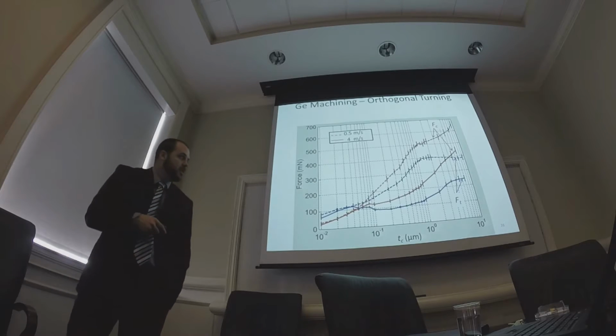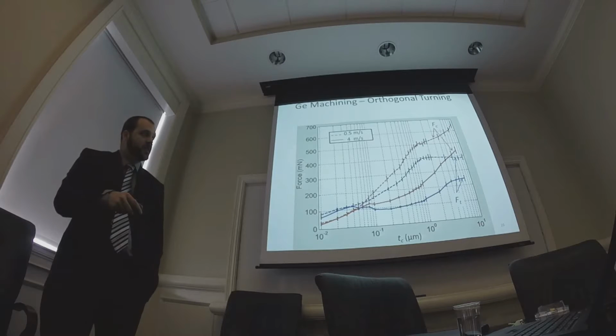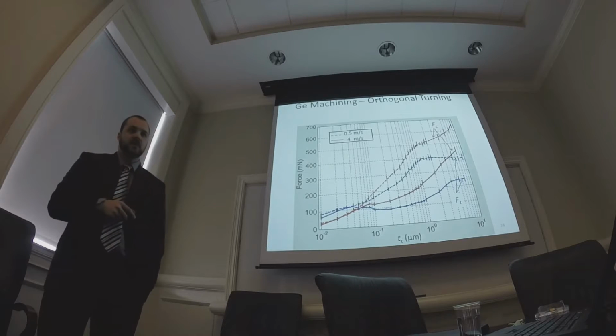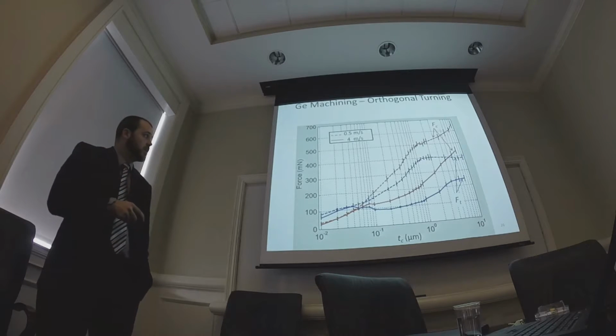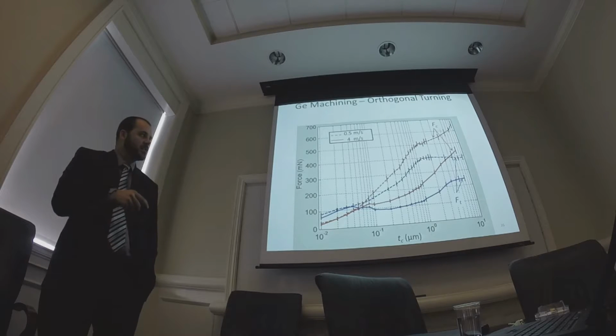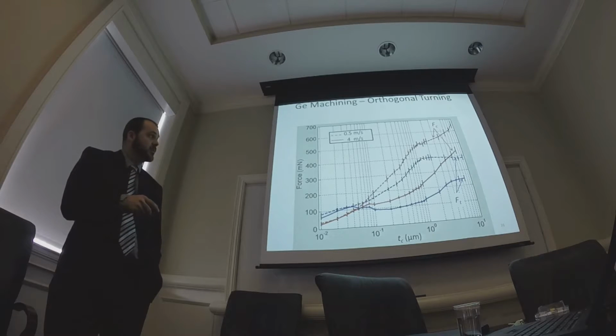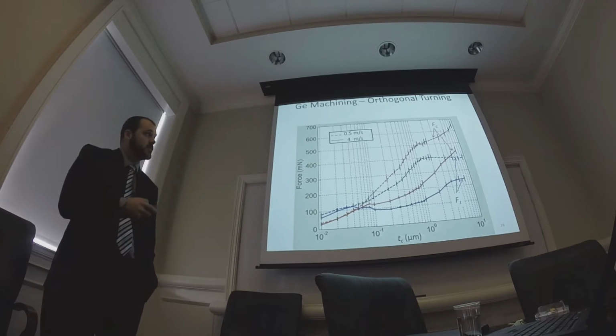Here is all of our chip thicknesses that we measured at 2 different speeds. When we're in that range, we've got this extreme negative rake. We're not seeing much variation between the speeds, but once we leave that 50, 60 nanometer range, we see a pretty big deviation as we work our way along.